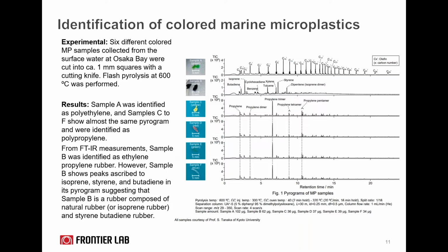The samples were cut into very small pieces, and then we placed them into the sample cup. Pretty much that was all the sample preparation needed: making them smaller pieces to put inside our sample cup. Then we performed flash pyrolysis at 600 C, and again with the micro furnace, you are performing true single-step flash pyrolysis. And this analysis is for qualitative analysis in this specific technique that I'm showing here.